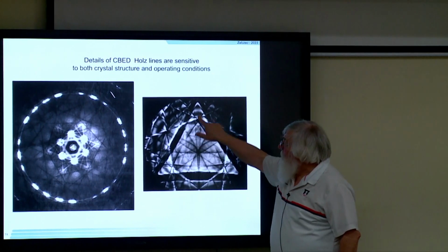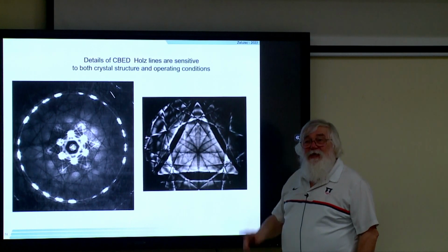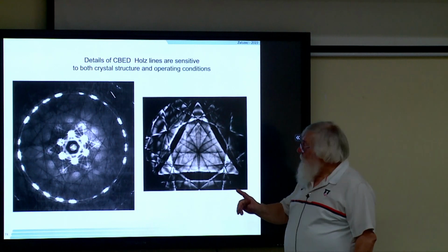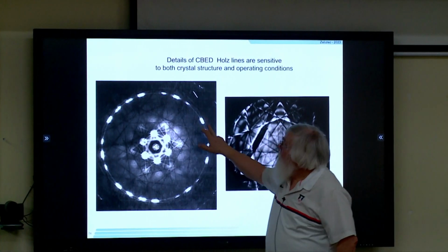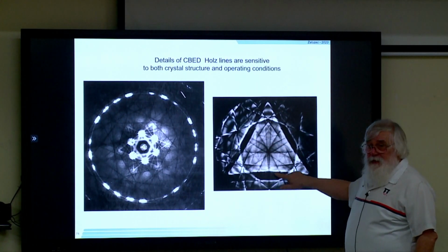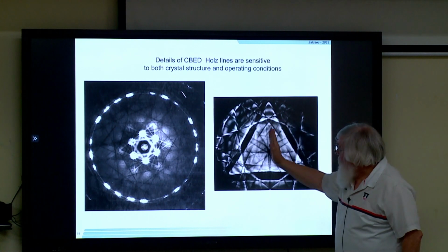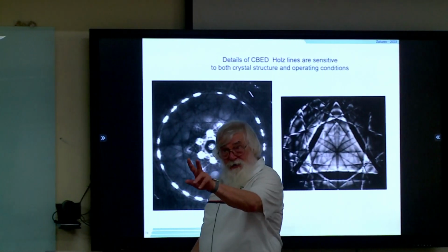I want you to look very closely. Is that threefold symmetric? The answer is no. Now, could you have seen it from this pattern? Nope. Can you see it from this? Not quite. But we can see it here in the higher order Laue zones that are in the 0, 0. You see a mirror plane right here.